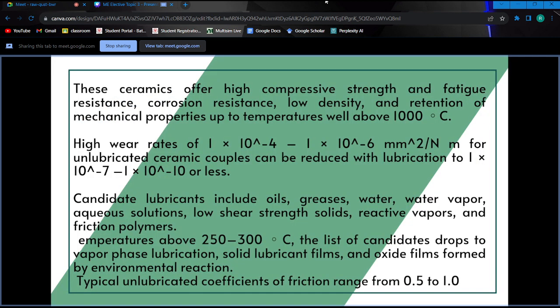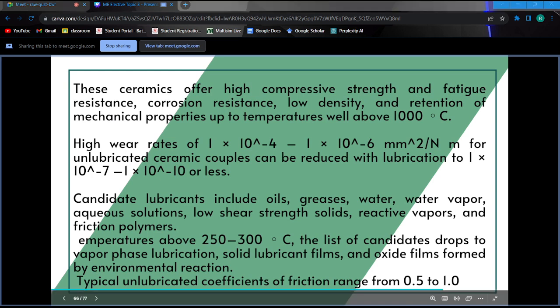These ceramics offer high compressive strength and fatigue resistance, corrosion resistance, low density, and retention of mechanical properties up to temperature well above 1,000 degrees Celsius. High wear rates of 1 times 10 raised to negative 4 up to 1 times 10 raised to negative 6 square millimeter per Newton meter for unlubricated ceramic couples can be reduced with lubrication to 1 times 10 raised to negative 7 up to 1 times 10 raised to negative 10 or less.